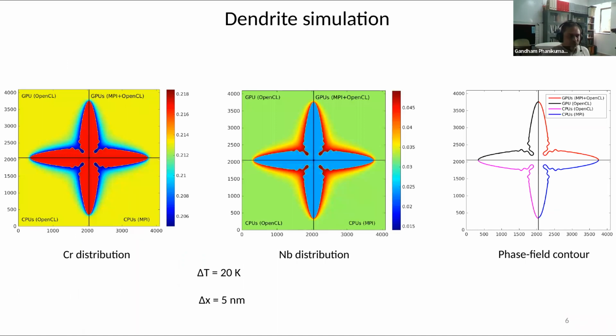Earlier I showed you the dendrite formation. So here is a computational dendrite. This is done in the computer, to show you the segregation of elements like niobium or chromium in a superalloy. The enrichment of niobium is shown here. Wherever it is red, there is more niobium. Wherever it is green, that is the average value. So you can make out that niobium is segregated between the dendrites. That is important, because excess niobium can lead to Laves phase, which is bad news. So the ability to simulate the segregation is important.